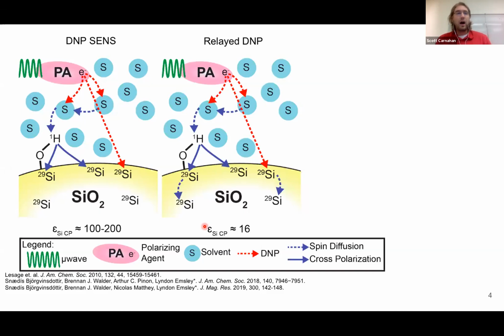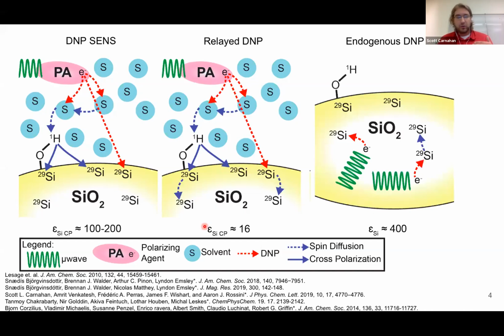So one other technique would be to introduce your radicals, instead of in a polarizing agent in the surface, but actually into the core of the materials. This has been done a number of times using gadolinium, manganese, chromium as the doping agents. But our idea was to create these radicals using gamma radiation. So then we have radicals inside the core, and we can do direct DNP and directly polarize the silicon in the core of these materials.